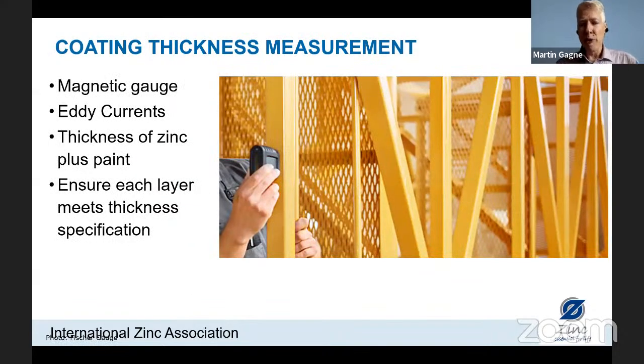Now, when we do make a duplex coating, the coating thickness measurement becomes very important. Most magnetic gauges will measure the total thickness of the coating. So that is the thermal spray zinc and the paint layer. So it's important to measure the thickness of the zinc as it's applied to make sure that it meets the specification, generally 100 microns. And then afterwards, when the paint is applied, measure the total coating thickness, subtract the thickness of the zinc, and then we make sure that the paint coating thickness also meets specification.